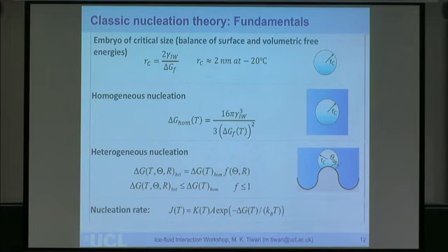So we really need precision of surface texture if we want to control ice formation, in addition to the wettability and low adhesion, etc., that we were talking about earlier. And these are one-to-one related to the rate at which these nuclei form as well, as you'd expect from these Arrhenius-like equations. This delta G is the same delta G that we're looking at over there.